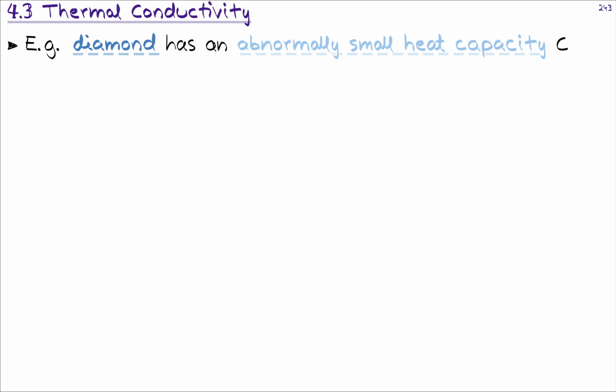So let's elucidate this by providing a practical example. And you know my fetish towards diamond. That's my favorite material in terms of solid state physics, and it's among my favorite top 5 materials in general. Diamond has a surprisingly small heat capacity C at room temperature, really abnormally small, and the Debye model cannot predict the heat capacities that well. Let me rephrase: the diamond heat capacity does not yet approach the Dulong-Petit value at room temperature. So it's way lower than what one would expect for materials at room temperature.